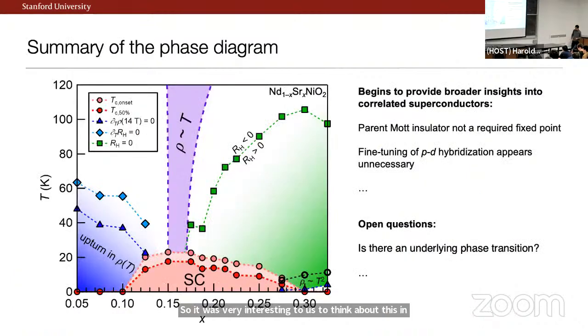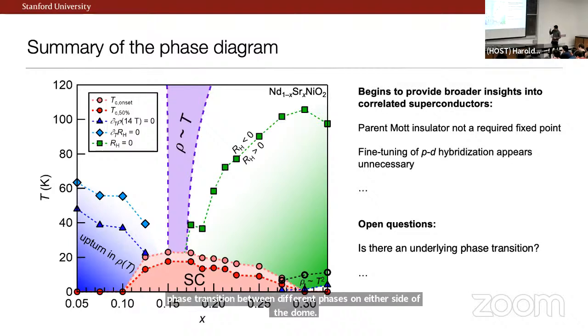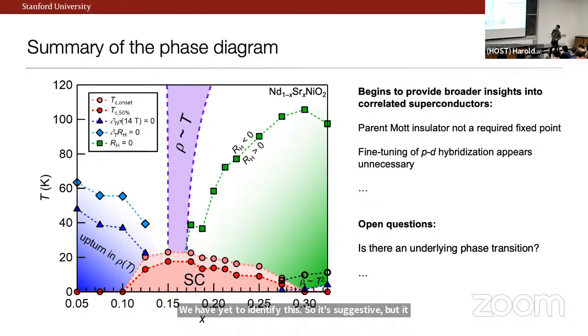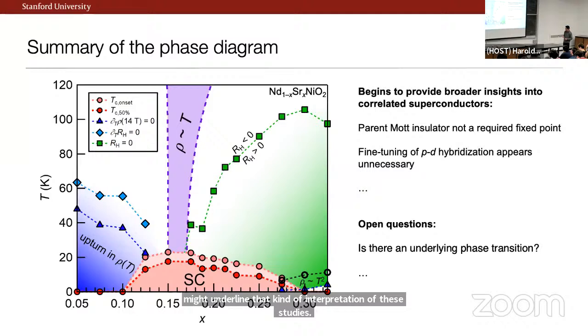So again, let me skip those details, but just to say that these kind of very fundamental materials advances are allowing us to start to discuss intrinsic properties and think about a number of issues. I haven't gone through all of this, features in the Hall coefficient and other magnetotransport phenomena. But you can kind of see that it seems like something weird is happening right where we have superconductivity, right? All lines are leading down. And again, this is pretty characteristic of a lot of these sorts of families of compounds. In other situations, it's often thought of as being driven by an underlying phase transition, a quantum phase transition between different phases on either side of the dome. We have yet to identify this. So it's suggestive, but it begs the question of what is the broken symmetry that might underlie that kind of interpretation of these studies.